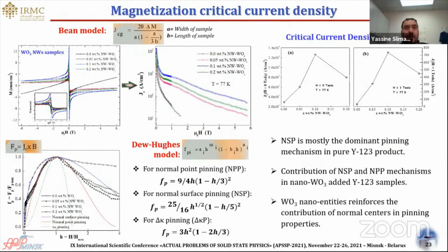Here, for example, we presented the measurement of magnetization versus applied magnetic field, which were performed at the temperature of liquid nitrogen, 77 Kelvin. By means of these measurements, the critical current density was estimated using the Bean model, and this parameter is an evaluator to judge if the material is useful for practical application or not.